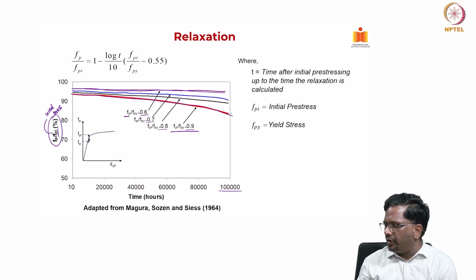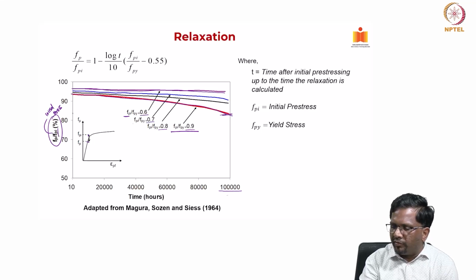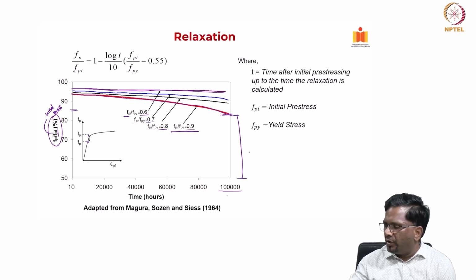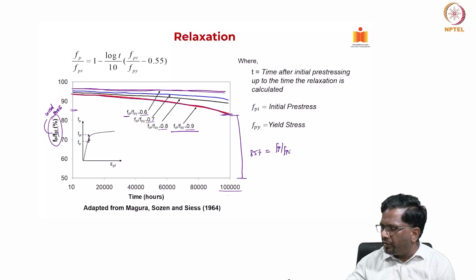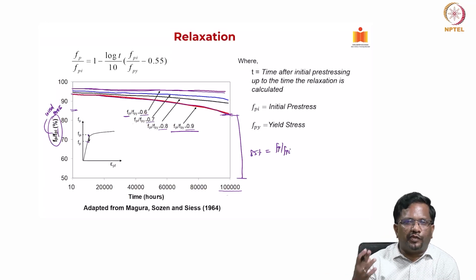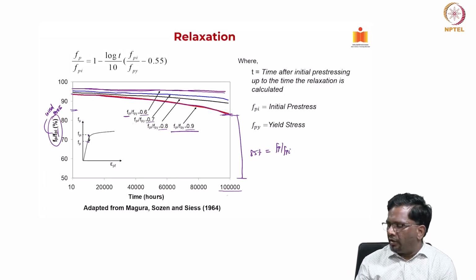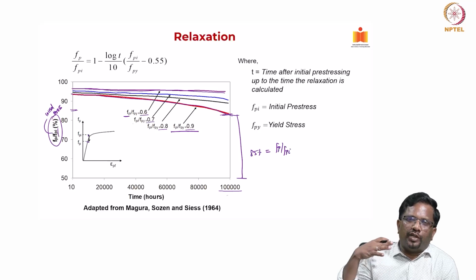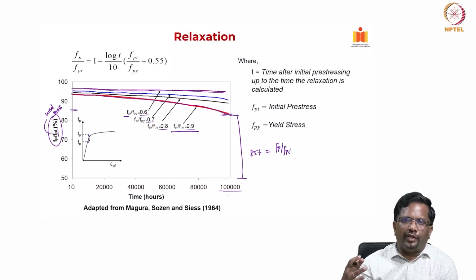For example, you see at the end of, let us say, 40,000. So, this is in hours, right. So, you get roughly about 85% or so. This is about 85%. What is 85%? FP by FPI. Okay. That means I have lost 15% of the initial stress at the end of 100,000 hours, which is 1 lakh hours, right. So, that means if my initial stress is very close to that of yielding, the loss due to pre-stressing is going to be very high.